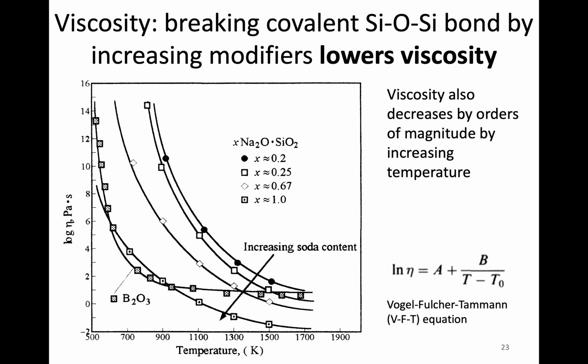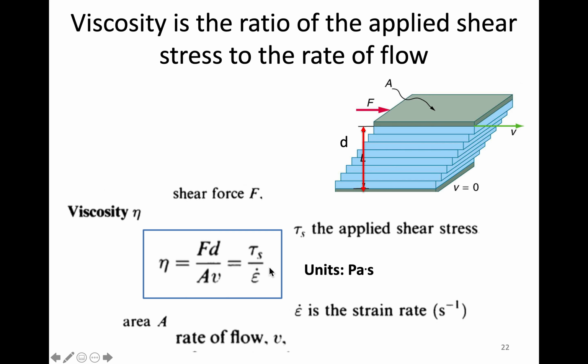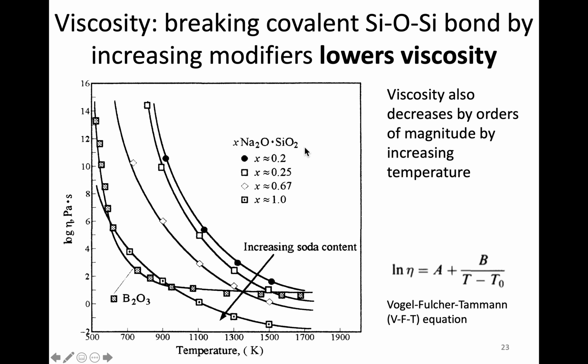All right, so for glasses, viscosity is tied to those bonds that we saw. Everything is coming back to the silicate structure. When we saw the Si-O-Si bond, that was a bridging oxygen. And we break those bonds when we add modifiers. In this plot, we're looking at the increase of sodium, which is a modifier, into the glass. Increasing that breaks up these bonds, and therefore it makes it easier to flow, the part down here.